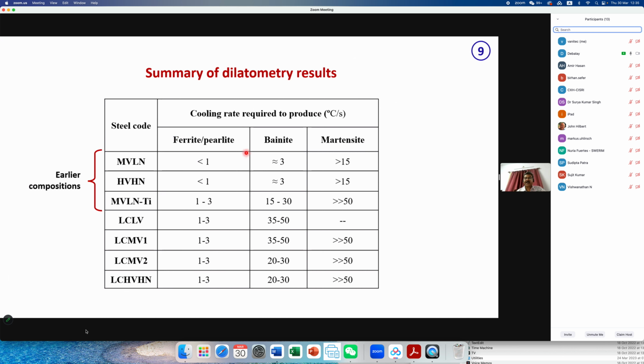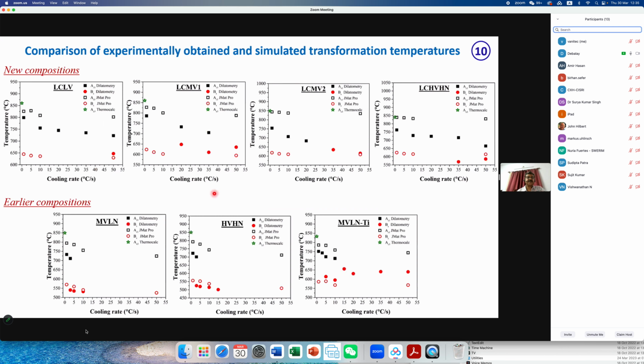Typically, we are getting ferrite pearlite microstructure in the later steels we have made. Initially, you may remember vanadium was there in solution, so we had bainitic microstructure and hardenability was quite high. In these steels, hardenability is manageable. So typically we get ferrite pearlite microstructures. We have compared what we are getting from dilatometry and what we have predicted.